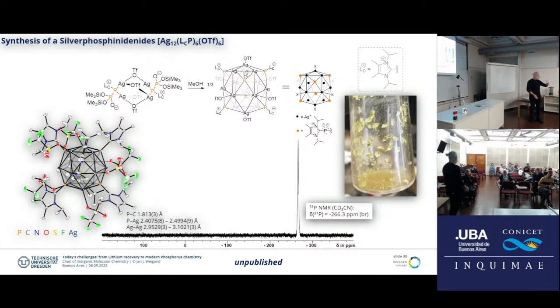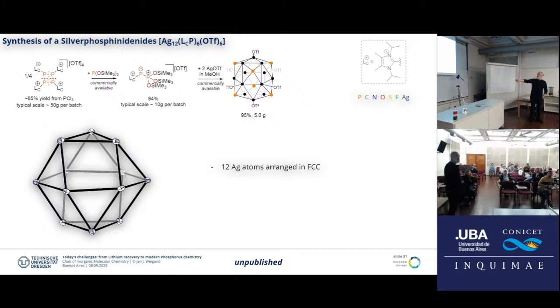You can make this, by the way, directly from scratch. You start with a tetracation, you use a silylated phosphide, you get this compound as an intermediate, you plunge in silver triflate in methanol, and you make this one more or less quantitative. I draw your attention also to this yield. More or less the whole batch is quantitative.